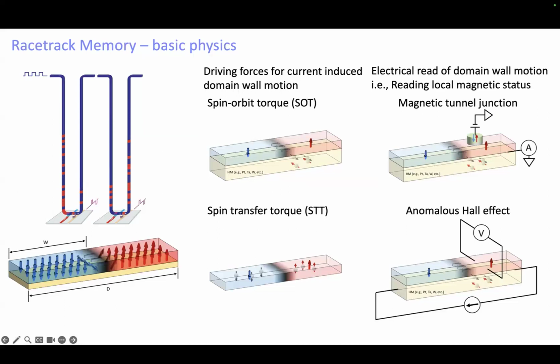So the one which I discuss now is called spin transfer torque, wherein in a single magnetic material, the current, simply by passing through that magnetic material, becomes, through spin-dependent scattering, spin polarized. And when it crosses a domain wall, it can adiabatically transfer its spin angular momentum into the magnetization of the domain wall, causing the domain wall to move if you have enough current, enough spin angular momentum passed across the domain wall. And that's what we showed in a paper in 2008. We could move domain walls like this at speeds of about 100 meters per second.